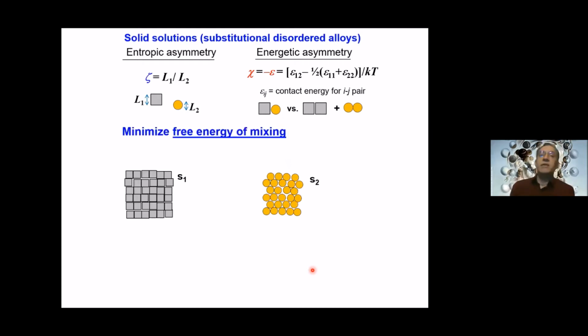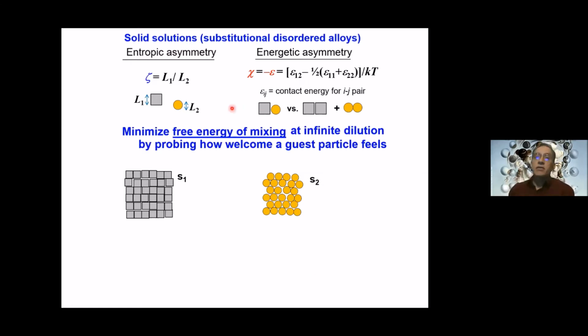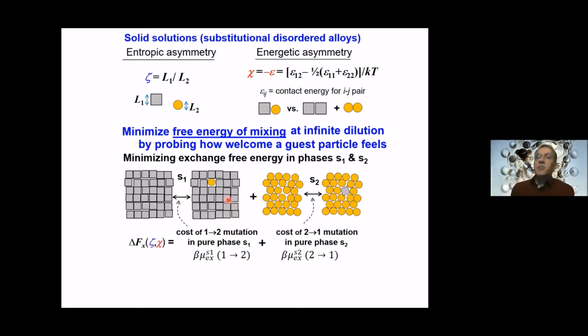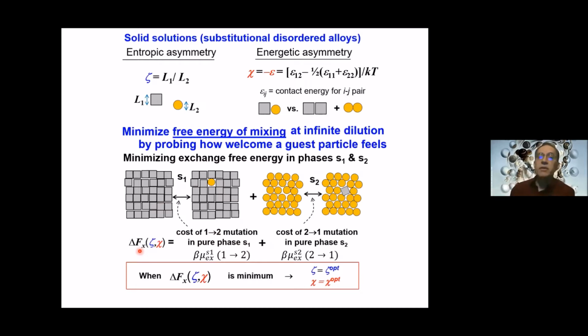So the question was really, what free energy needs to be optimized? And so we settled on the following, that we wanted to optimize the free energy of mixing. But not knowing the composition, it was best to try to do this at infinite dilution conditions, meaning that if I have these two phases for the pure components, I want to maximize, for example, how welcome this phase will be to the other component. And so you can measure this by introducing these virtual mutations, where you try to change a host particle into a guest particle, but you do that in both solid phases, and you add them up to create a quantity that, as I said, more or less represents this free energy of mixing at infinite dilution. We will call this the exchange free energy, delta Fx. And we postulated that if you minimize this quantity, you will find the optimal conditions for these parameters, zeta and chi.